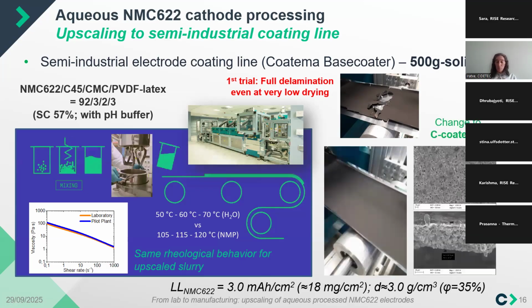To solve these issues, which were related to lower adhesion to the current collector, one of the ways to solve this with water-based cathode slurries toward manufacturing is to use carbon-coated or graphitized aluminum current collector foils. This reduces the possible corrosion issue at larger scale, due to having this thin carbon coating or graphite layer protecting the aluminum surface and also helping the adhesion of the electrode formulation to this graphitized layer.